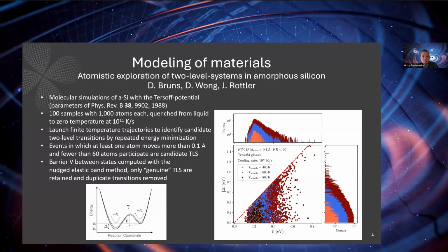This is work done by Jörg Rottler and former members of the group, Daniel Bruns and Daniel Wong. They're doing an atomistic exploration of two-level systems in amorphous silicon. Two-level systems are the things that are responsible for mechanical loss. What they're doing is molecular simulations of amorphous silicon using the Tersoff potential. They're looking for which two-level systems contribute to mechanical loss, and to predict the mechanical loss of a material, in this case, amorphous silicon.